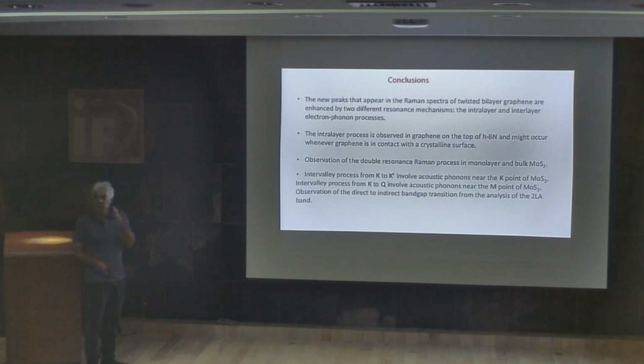In the case of molybdenum disulfide, we could also observe this intervalley process that we call double resonant process. The intervalley process from K to K prime involves acoustic phonons near the K point, but in the case of bulk, we can also have the process from K to Q involving phonons near the M point. And this is a consequence of the direct to indirect band gap transition. We can get this information from the analysis of the 2LA band.